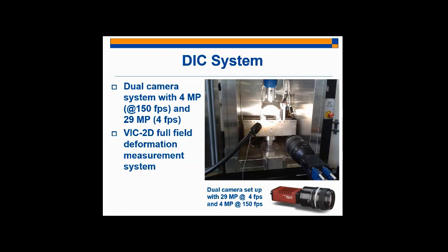We have a set of two cameras. One of them is a very high resolution, low speed camera. The other is a relatively low resolution, high speed camera. And this allows us to capture full field deformation measurements of our specimens as we test them. And so you can see the setup there. And this is being tested at 25 degrees Celsius, again, room temperature. We just record the deformations on the specimen for the duration of the test. And we can calculate things like strain fields from this that we couldn't regularly see with the naked eye.